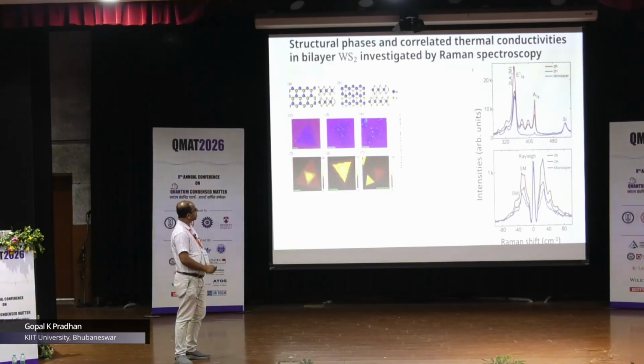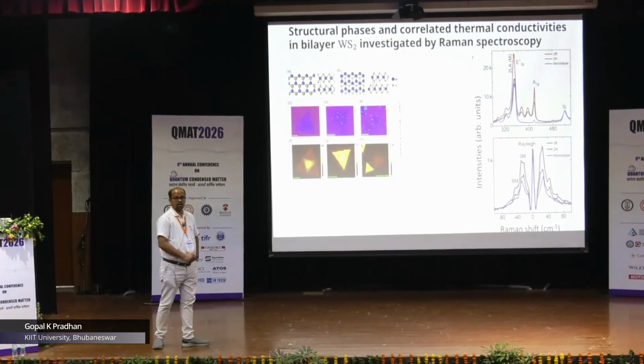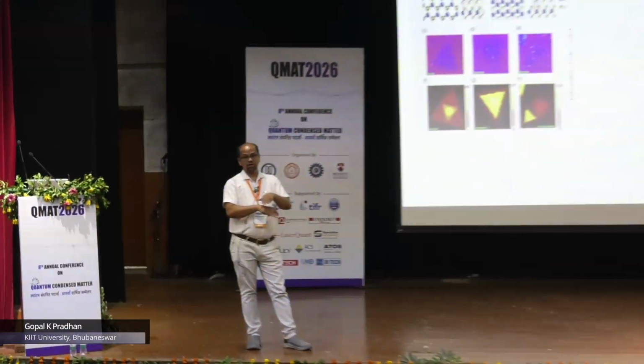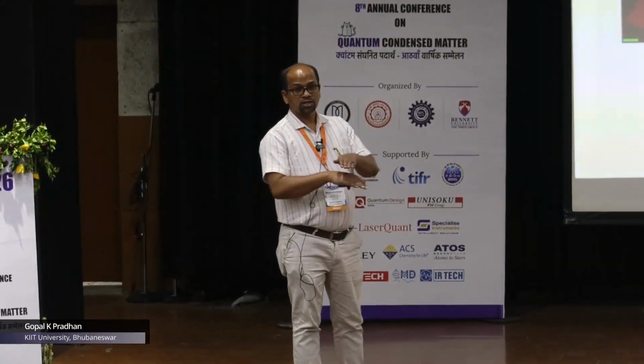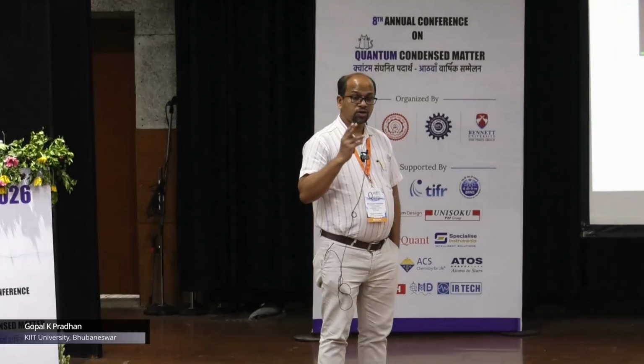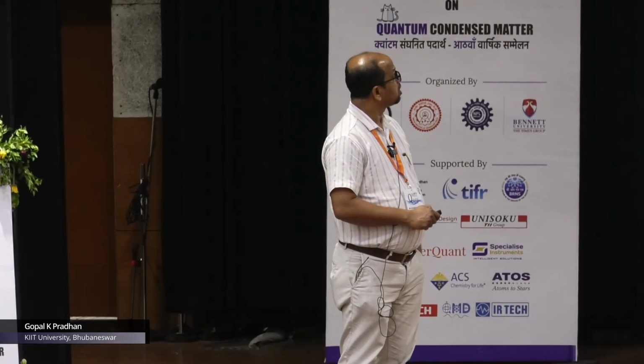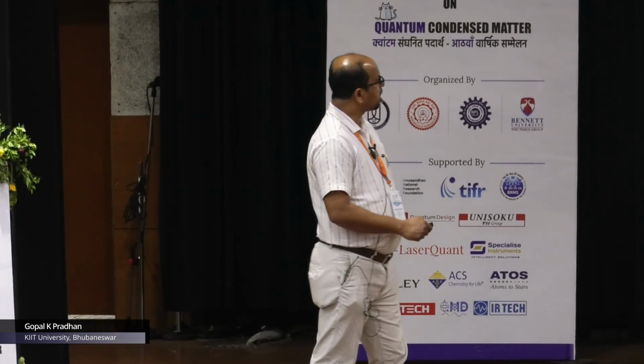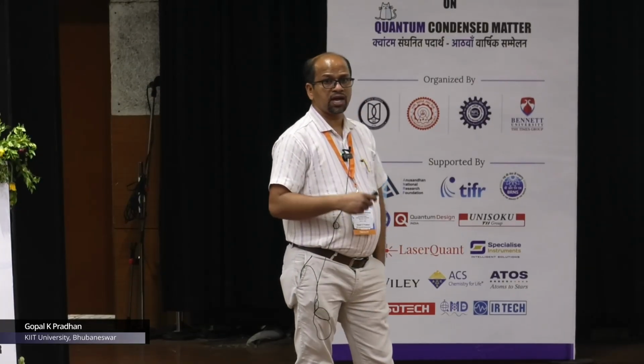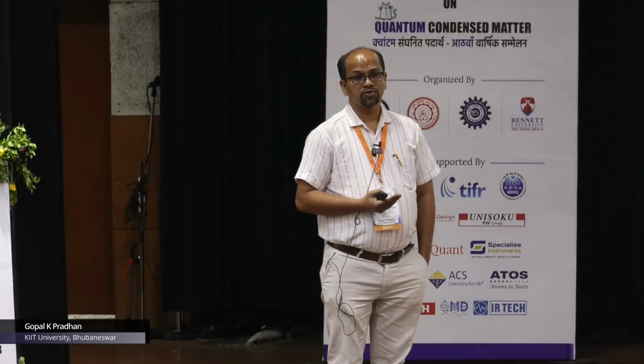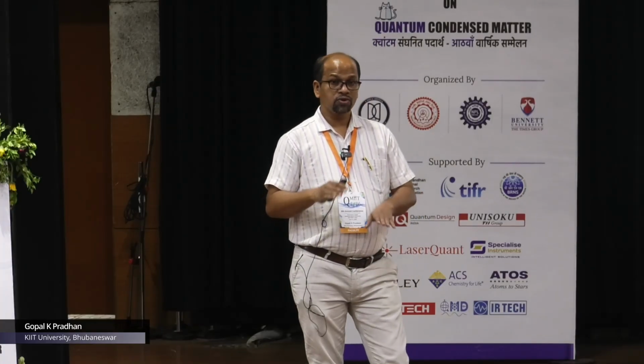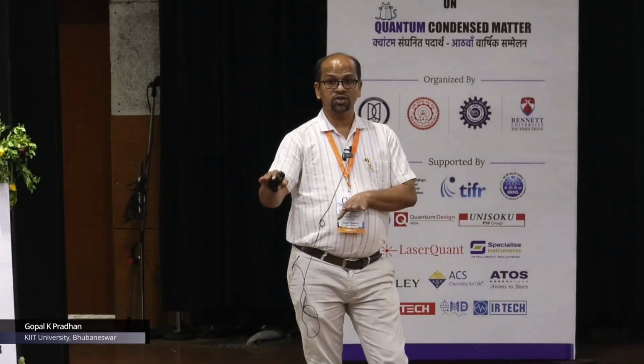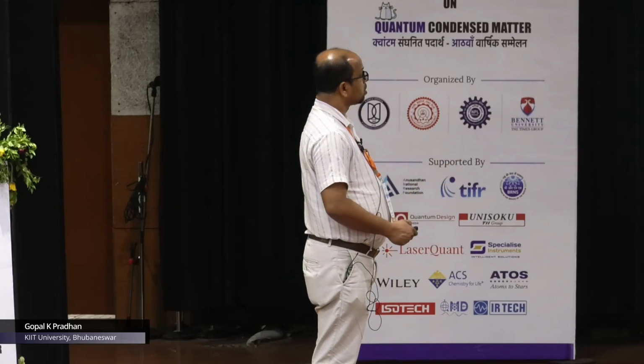But what is interesting here, you see the red one is 3R, the black one is 2H, and the blue one is monolayer. Okay, but I told you this is a bilayer, so WS2 over WS2. So this is a two layer system, but there are two different phases present here. One phase is 3R, the other phase is 2H, and we can distinguish them from their Raman signatures, which one is 3R and which one is 2H. So Raman helps you distinguish in the same sample: there could be regions where it is grown in the 3R phase, and regions where it is grown in the 2H phase, right?